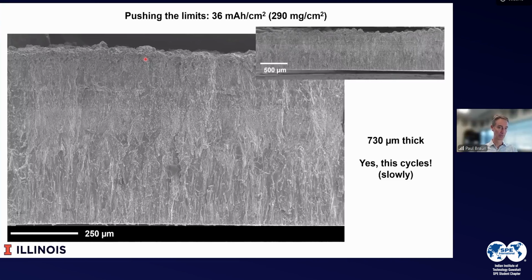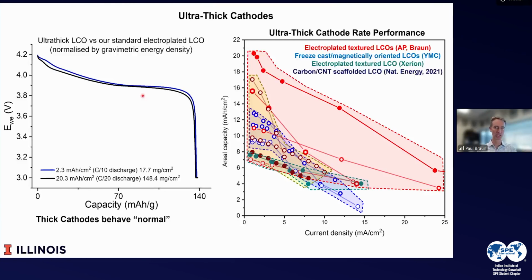unlike what would be possible in a slurry. If this was a slurry, it would have cracked and it would be disconnected and there would be a lot of dead material. If we continue to look at the thick material, the rate performance continues to be good. And when we compare that with what's in the literature, we can see that at any given capacity, the maximum current density is much higher.